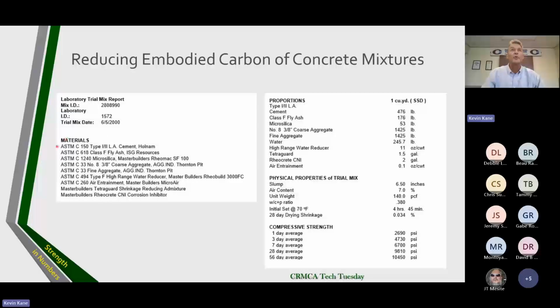So here's where my materials were. I took C150 Type III LA cement from, at that time, Holnam. Class F fly ash from, at that time, ISG Resources. I took microsilica from Master Builders. I took a pea gravel and a sand right out of the Platte River pit from Aggregate Industries Thornton pit. I used Master Builders 3000 FC, Master Builders Micro Air, and just for kicks, I put in an SRA, Tetraguard, and I put in a corrosion inhibitor. Now, are we ever going to have to make that kind of concrete mix? Probably not, but like I said, you don't know until you try it. Let's see what we get.